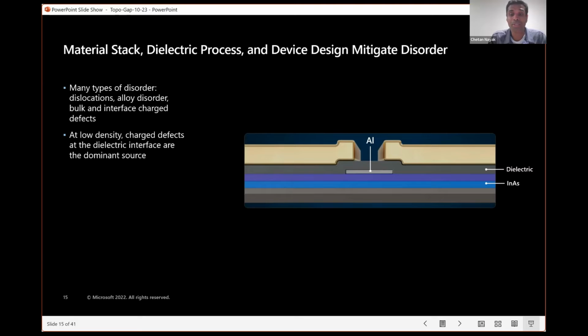It turns out that at low density, and we're in the low density limit because it's a quasi-1D system, lowest subband, the dominant source of disorder is charge defects at the dielectric interface. Okay, so there's a dielectric here, which insulates the system from these gates. That dielectric has defects that are charge defects right at the interface of the semiconductor. They're the dominant source of disorder in this system. Okay, and so what the design does is keep these defects as far from the active region as possible. So we want to maximize this distance.